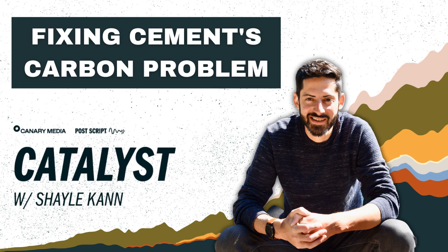But you can only blend in so much. You're blending it in to remove some of that extra calcium, but if you add too much silicates, now you have too much silicates. And so it's that reaction between the calcium and the silica that makes the hardened cement. So you can only blend about 30% in before you start reducing, diluting the performance.